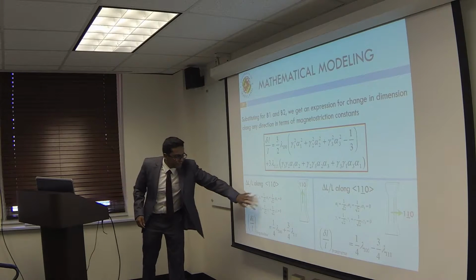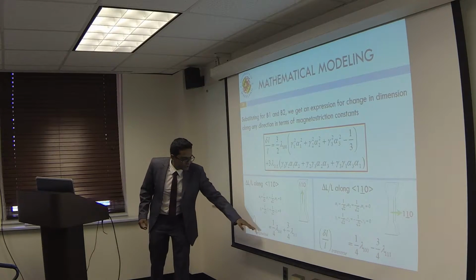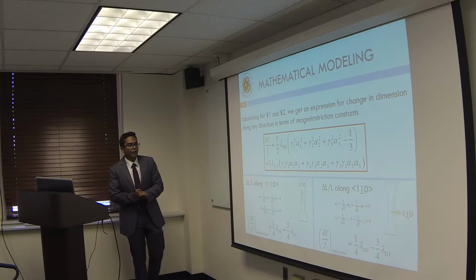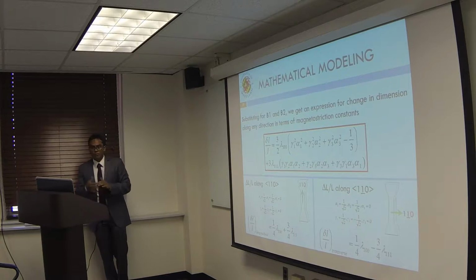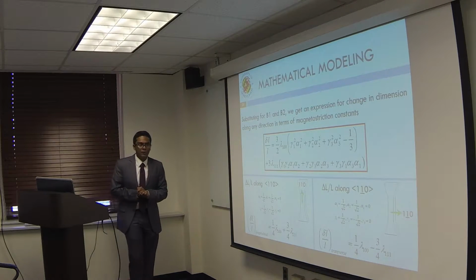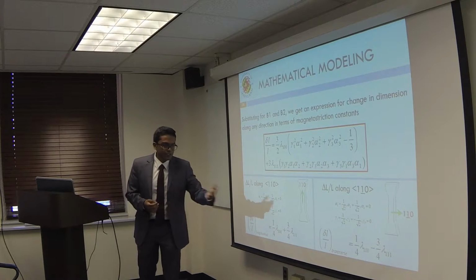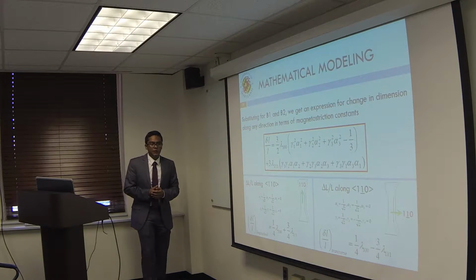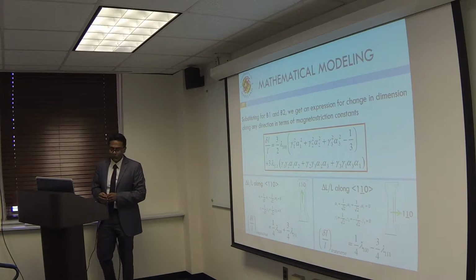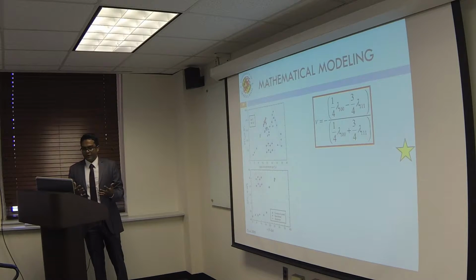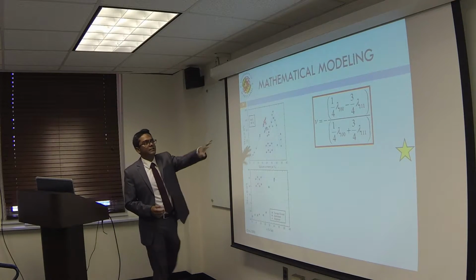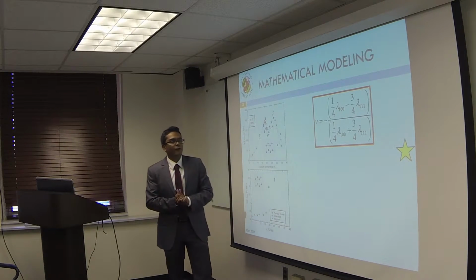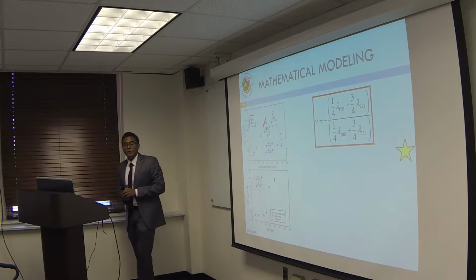So when I plug in for the direction cosines, I find that the longitudinal strain is defined by 1/4 lambda 100 plus 3/4 of lambda 111, and the transverse strain is 1/4 of lambda 100 minus 3/4 of lambda 111. So I decided to take the negative ratio of these two, and I end up with this cute little equation for figuring out the Poisson's ratio.